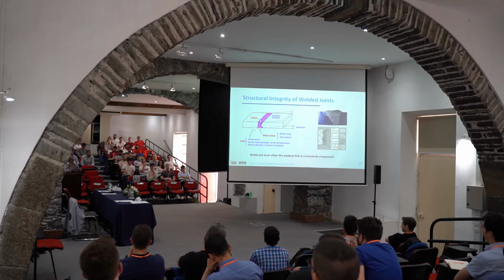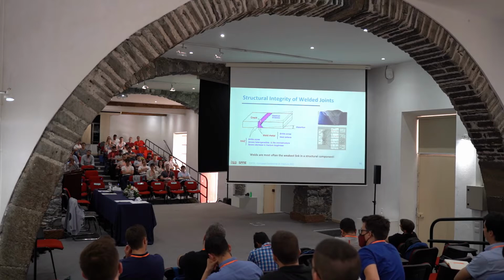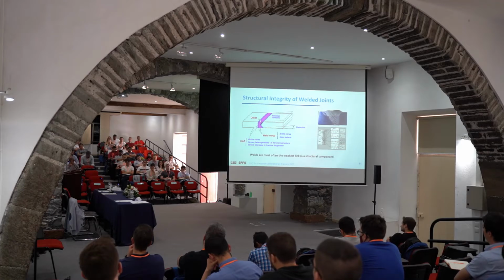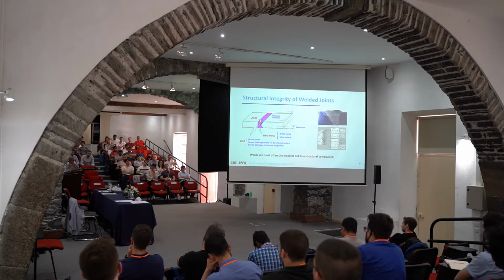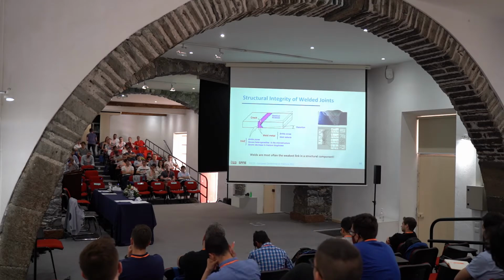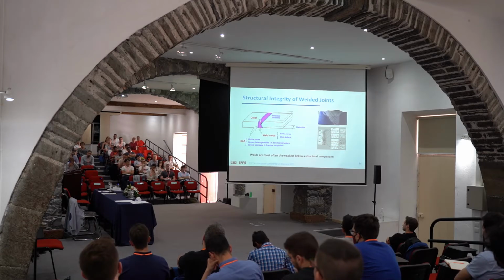Of course, everybody here in this room remembers the iron-carbon equilibrium diagram. Okay, so we have the transformation, ferrite, then we have austenite. When it's one cycle, very controlled, the microstructure transformation is very fine. If the cooling is very slow, all these microstructures are transformed in a very nice way, and when you work at room temperature, you have a very nice microstructure, so you understand very well what's happening, because of course we tested before. With welding it is different, because first the cooling is very different. So you melt down a very concentrated piece of metal. It quickly cools down, so the transformation is very different from the initial controlled transformation.